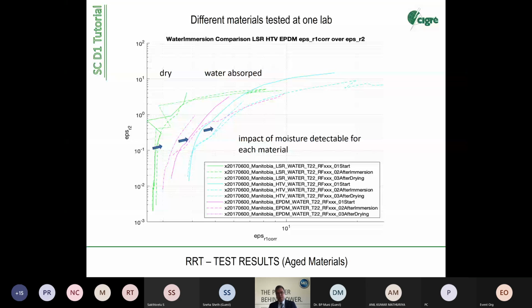So in Manitoba, Canada, they performed the test on LSR, HTV, and EPDM, and you can see they differ. All three materials are not in the same area or on the same line. So they are different in initial conditions, but they show the same tendency. And also here you can detect moisture in each material.